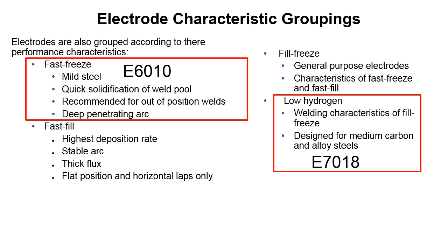I'm trying to explain it, but the weld metal is more fluid, so it has a tendency to droop on you, and it doesn't freeze as quickly as 6010. So this is another major difference between 6010 and 7018: how fast the weld metal freezes and how penetrating the arc is. The arc on 7018 isn't a very deep penetrating arc, not nearly as deeply penetrating as 6010. So there's your electrode characteristic groupings and some differences.